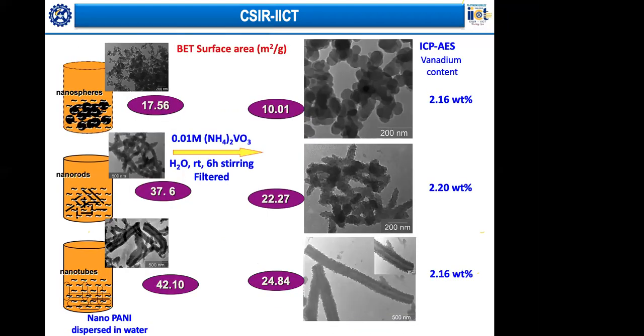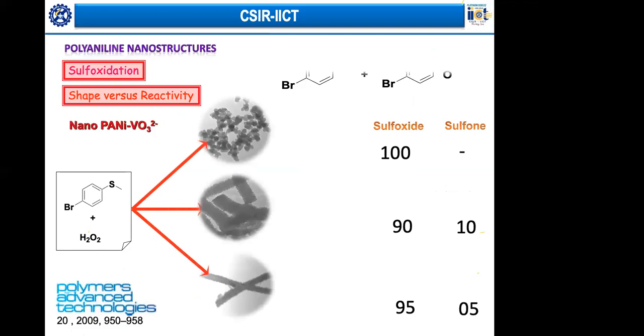And we try to measure the surface area, because when we talk about catalytic activities, surface area is very important. Here we are trying to dope with vanadium as a precursor, and then we look at the surface area. You can see that spheres are about 10 meters square per gram, rods 22.27 meters square per gram, and these tubes are a little higher, about 24 to 25 meters square per gram. Like in our earlier example in silica, higher surface area means better catalytic activity. So obviously it is these tubes which are showing better catalytic activity.